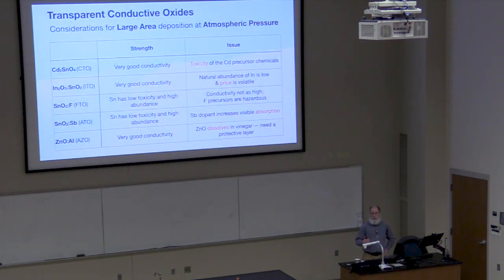So let's go back to our table of candidate materials. You can see we ruled out cadmium due to toxicity. That process I showed you, I'll show you a coater in a minute. You can see that materials can leak out into the atmosphere. We don't want that. Indium, as I said, the price is bad. We ruled out that due to absorption, and that dissolves in vinegar. So that brought us to tin oxide, fluorine-doped tin oxide. And that fluorine-doped tin oxide is used in other industries, like for coating glass bottles, for instance, which could be a different talk. So we settled on that.